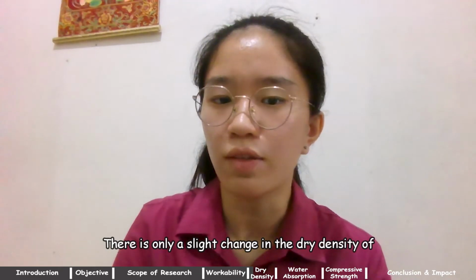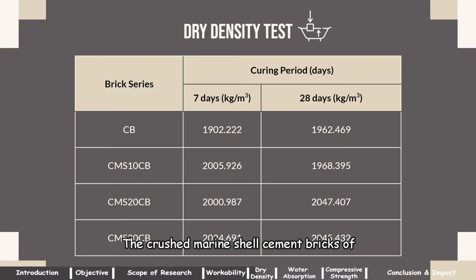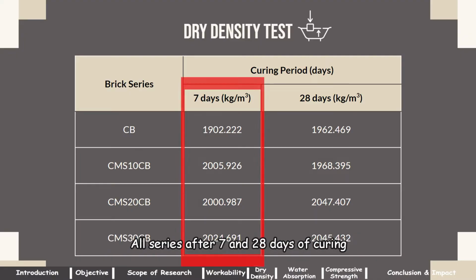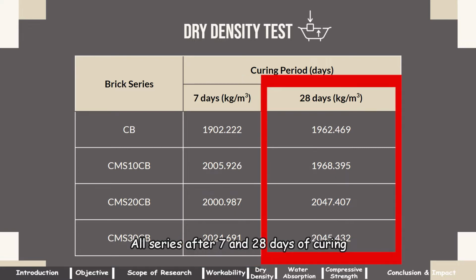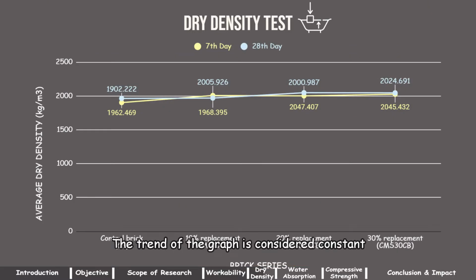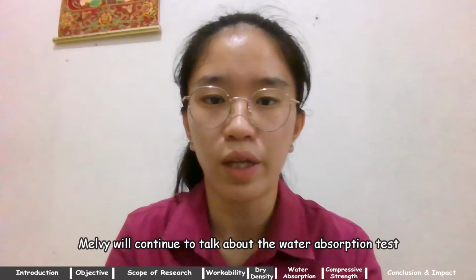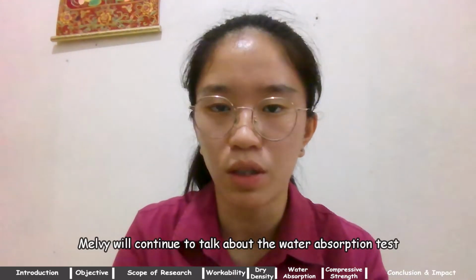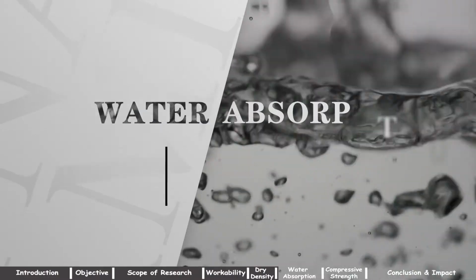There is only a slight change in the dry density of the crushed marine shell cement brick of all series after 7 days and 28 days of curing. The trend of the graph is considered constant. It is concluded that the percentage of crushed marine shell added does not affect the dry density of the brick. So next, Melby will continue to talk about the water absorption test.